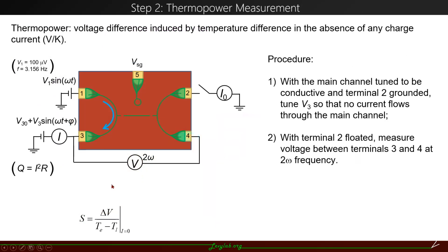The next step is to measure the thermopower, which is defined as the voltage difference induced by temperature difference in the absence of any charge current. To measure the thermopower, we first generate a temperature difference. Specifically, we apply the same sinusoidal source voltage to terminal 1, while we apply a drain voltage to terminal 3. We carefully tune the drain voltage, including its amplitude, offset, and phase, so that the potential at the left side of the quantum wire is 0. Then no current could flow across the quantum wire.